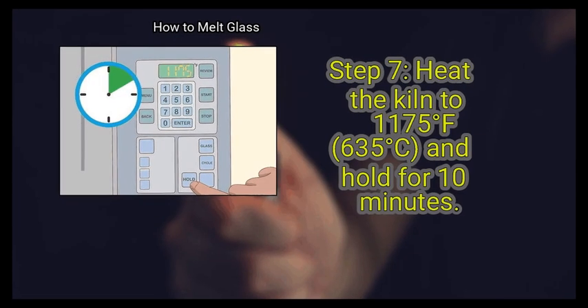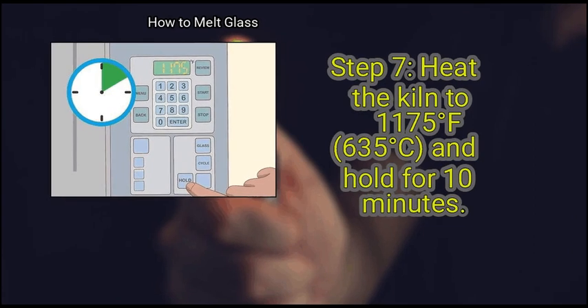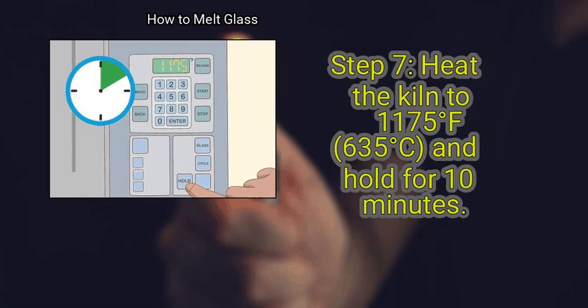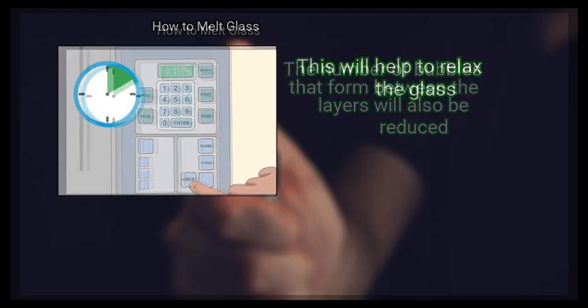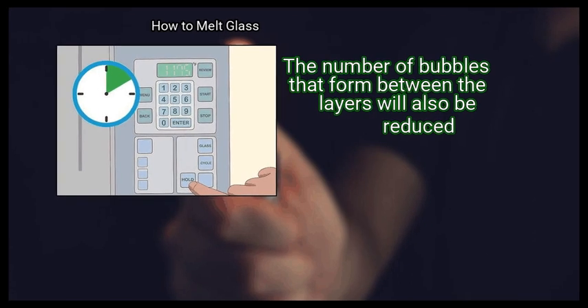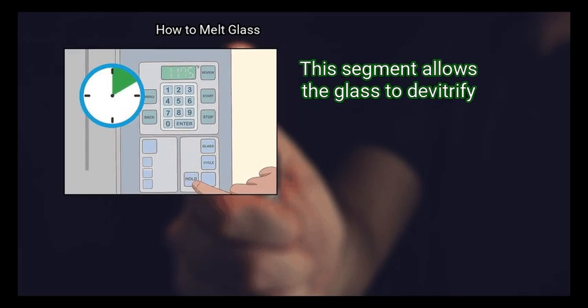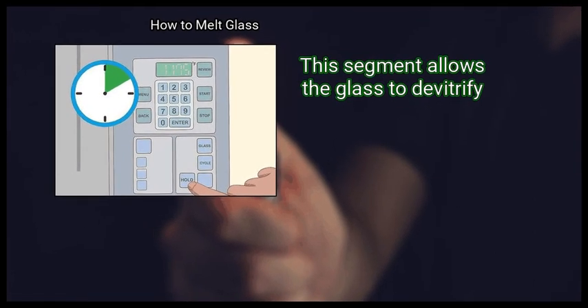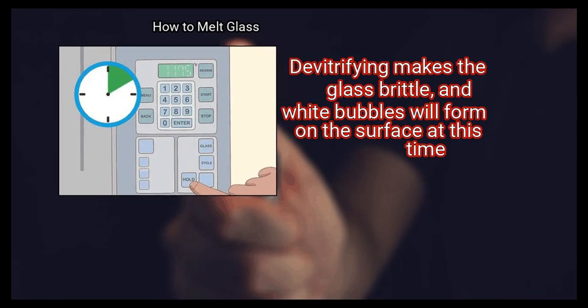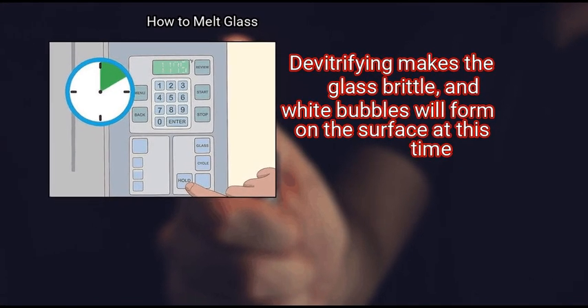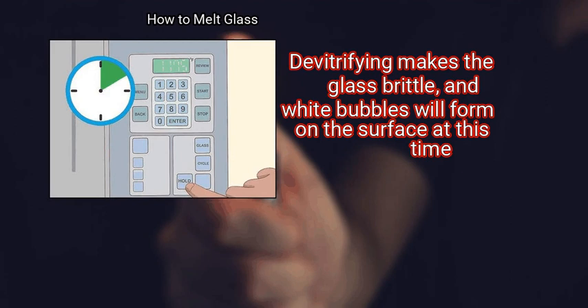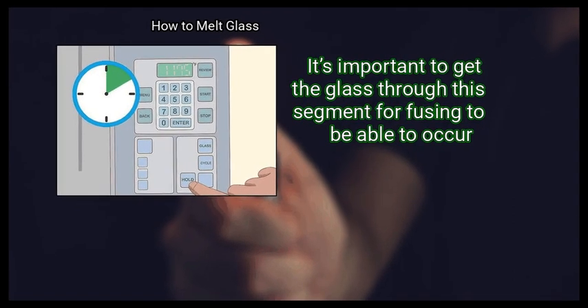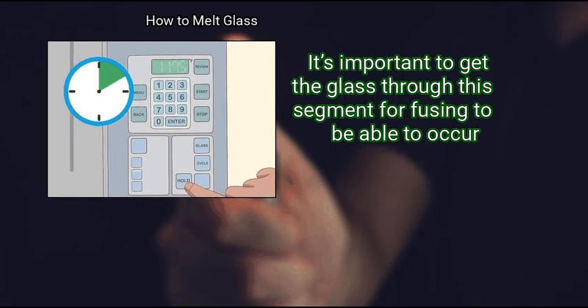Step 7. Heat the kiln to 1175 degrees Fahrenheit, 635 degrees Celsius, and hold for 10 minutes. This will help to relax the glass. The number of bubbles that form between the layers will also be reduced. This segment allows the glass to devitrify. Devitrifying makes the glass brittle, and white bubbles will form on the surface at this time. It's important to get the glass through this segment for fusing to be able to occur.